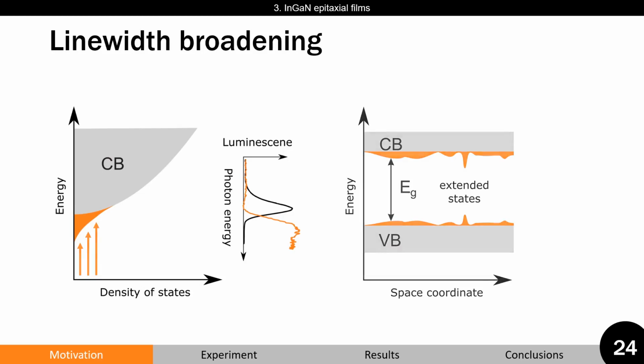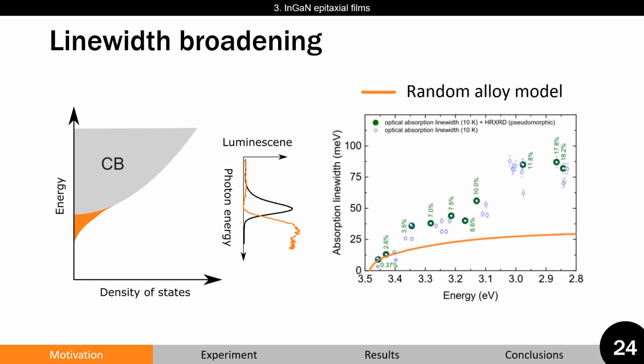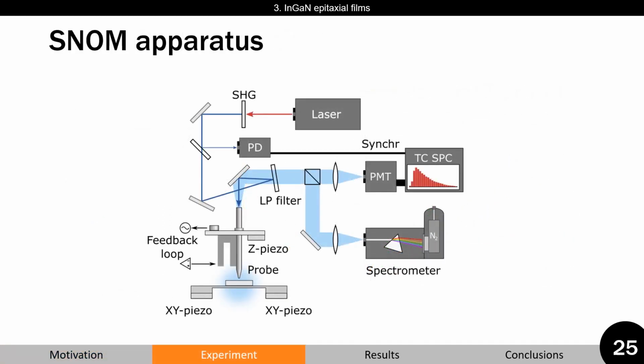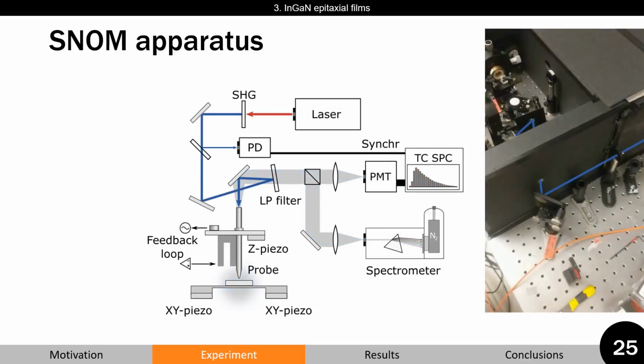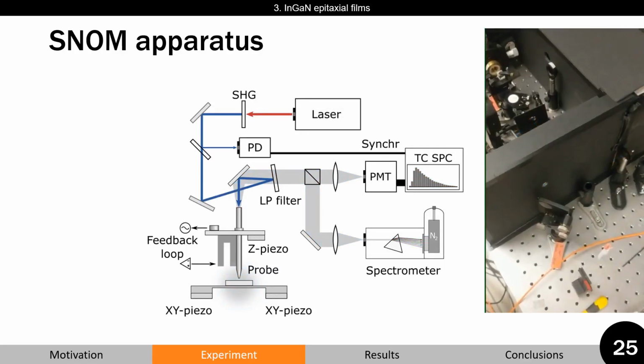For this reason, our colleagues at EPFL grew a large set of indium gallium nitride epitaxial films with different indium compositions and measured absorption line widths at low temperature. Then they applied the conventional random alloy model and found that only at very low indium content layers can line widths be described by the model. For increased indium molar fraction, line widths progressively deviate from predicted values. Therefore, samples were investigated here at PTH using a scanning near-field optical microscope, SNOM. We used the second harmonic, which with the help of a long-pass optical filter was coupled into the fiber.